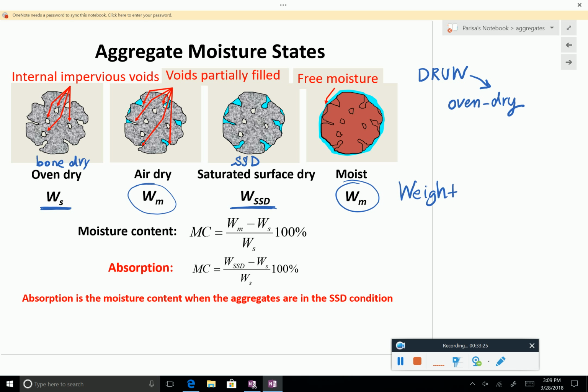Now, on the other hand, if you use ingredients which are wet, let's say you start with very wet potatoes. These potatoes are going to give water into the soup. So you need to reduce the amount of water that you plan to put in the soup to get the same consistency. It's exactly the same in concrete. So if you have aggregates which are very wet, that means they are more than saturated surface dry. They are going to release some of that water to the mix.